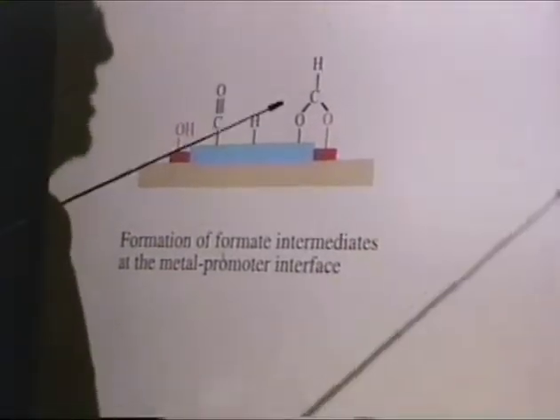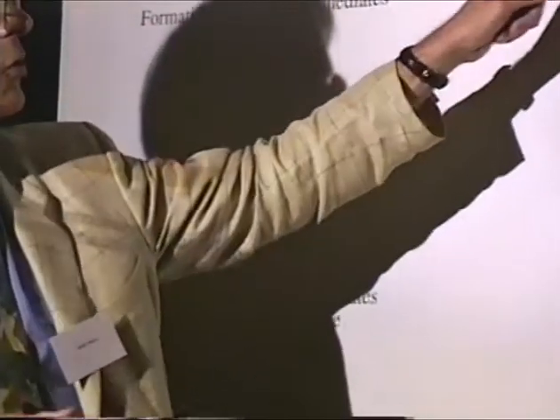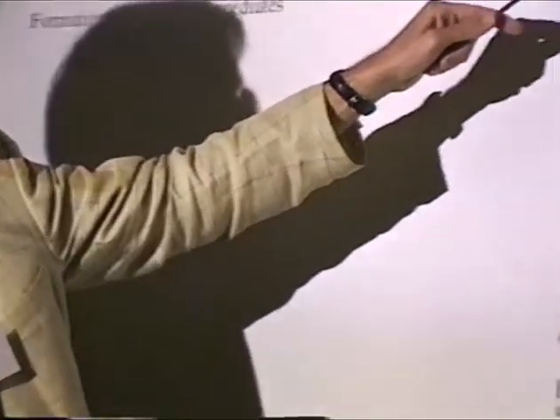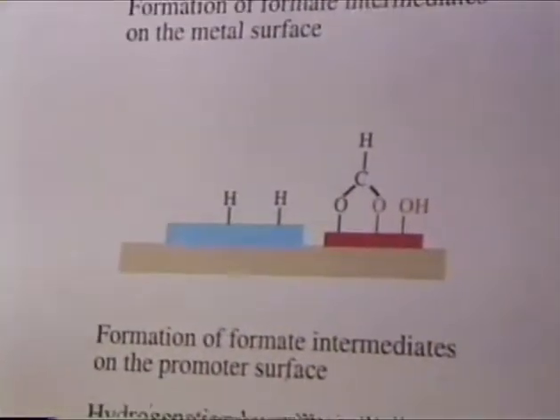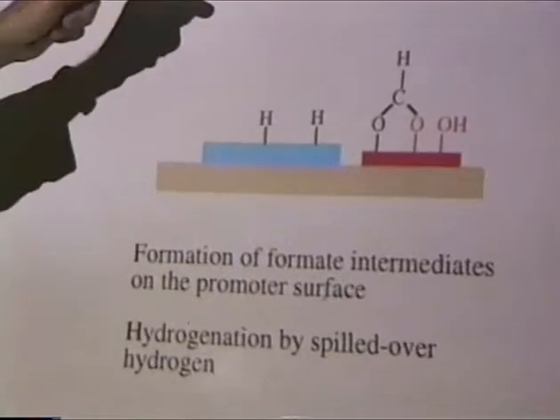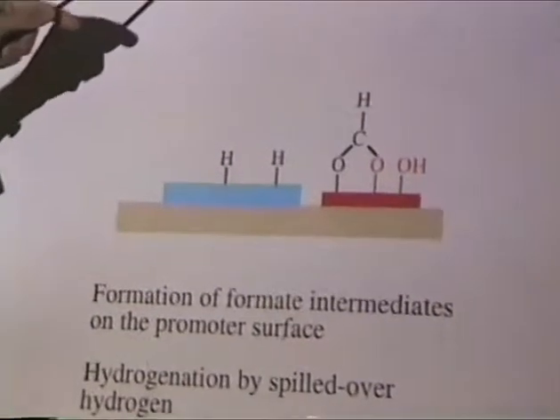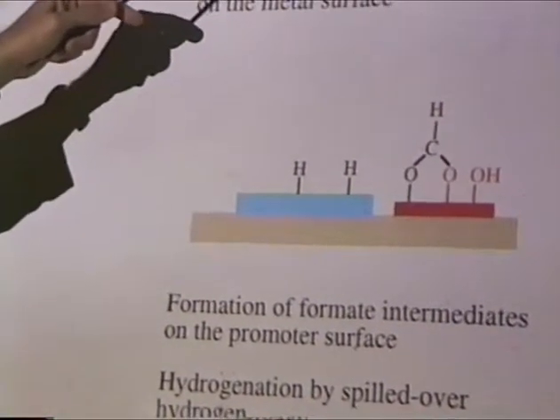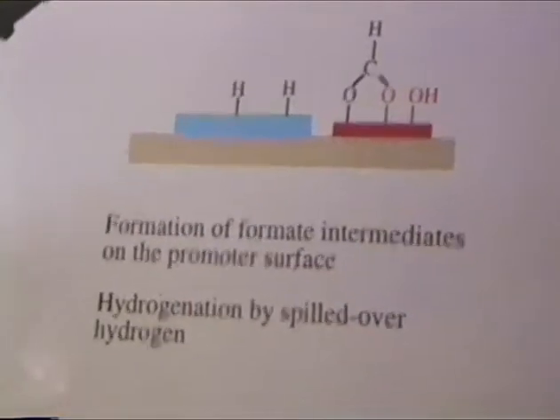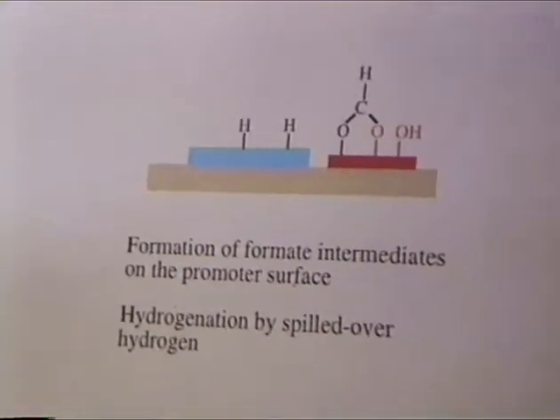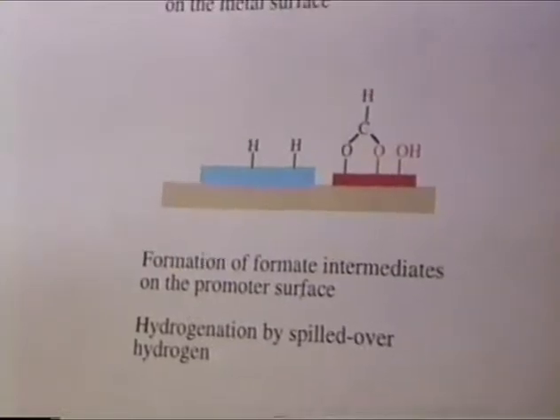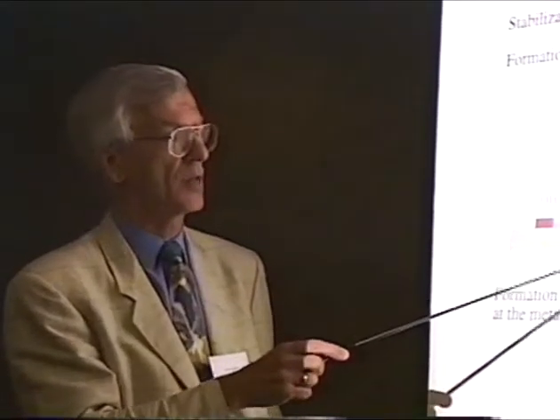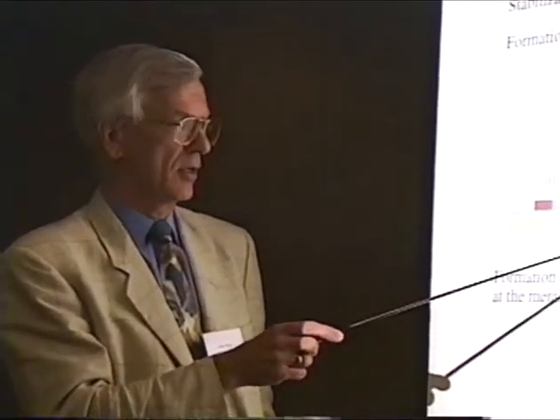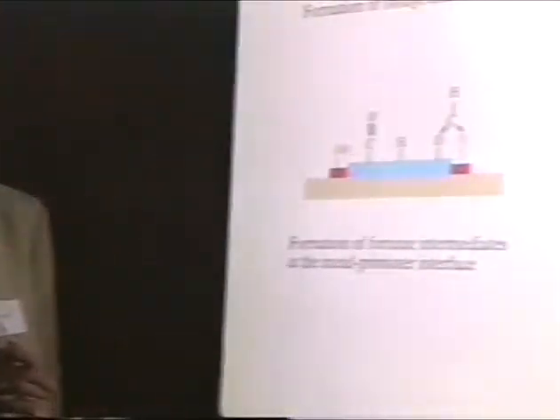There are other suggestions. The other three are all going through the formate, and there's one suggestion, again by Tamaru, that the promoter oxide, the calcium oxide for instance, is on top of the metal, and an oxygen atom from there gives you the extra oxygen needed to make the formate, and from there you hydrogenate it. A slightly different mechanism is that the promoter oxide is sitting next to the metal on the support, but this is more or less semantics, I would say.